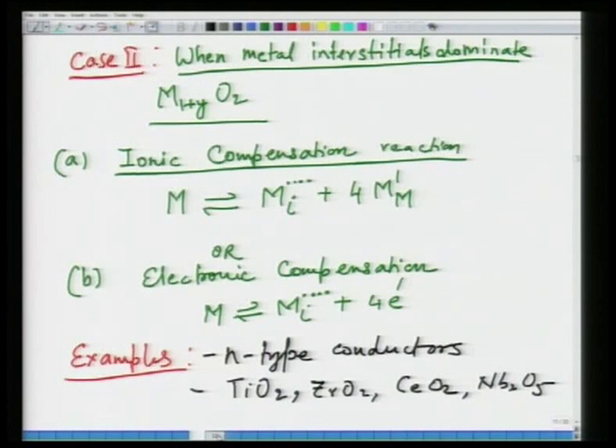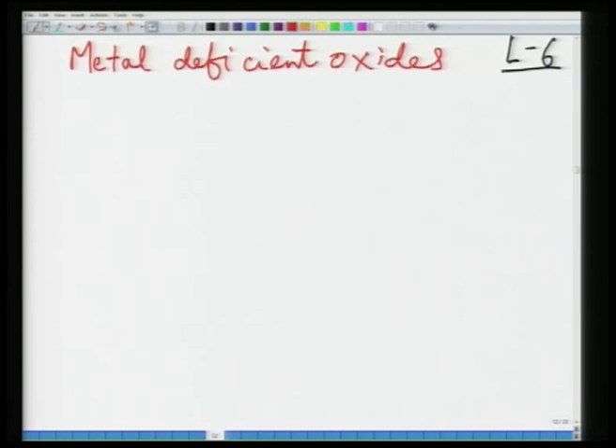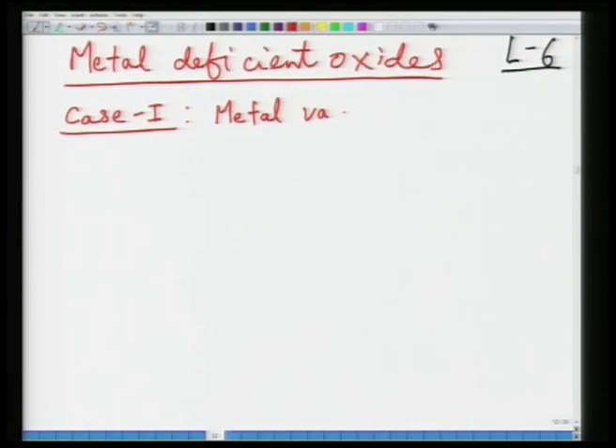So, now we will look at the case of metal deficient oxides. In case of metal deficient oxides, as you can guess intuitively, it would be either metal vacancies or oxygen interstitials if it was excess oxygen in case of excess oxide. So, metal deficient would in this case be another case of oxygen excess, and formation in this case typically happens at the surface. We will deal with two cases. The first case, case 1, is when metal vacancies are the dominating defects.